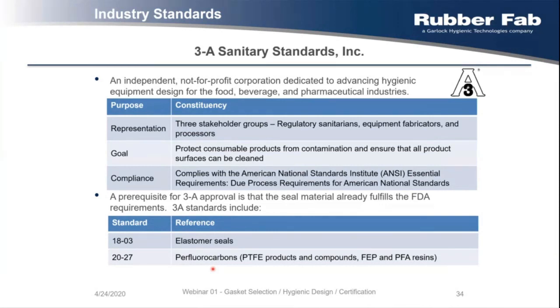It's also a fluid immersion test. So we also put the gaskets into a liquid, let it stay there for 7 days, sorry, at 70 degrees. And afterwards, we make a cleanability test. So let's say we put it into water again, take it out and make a cleanability test afterwards.